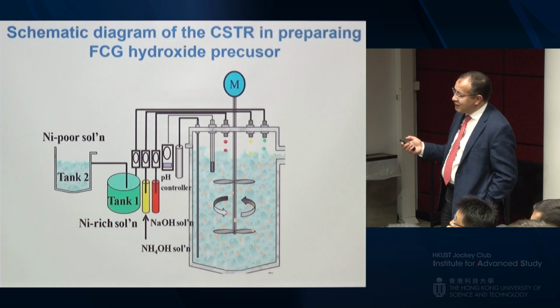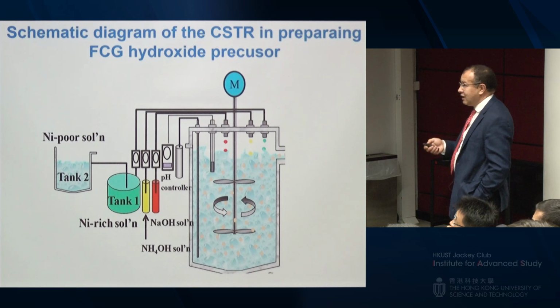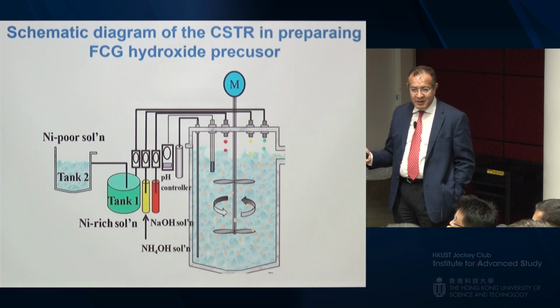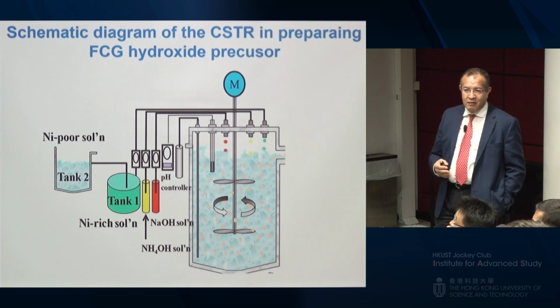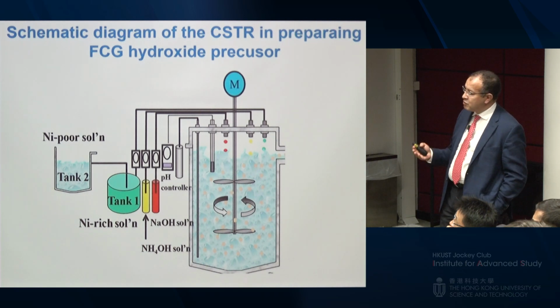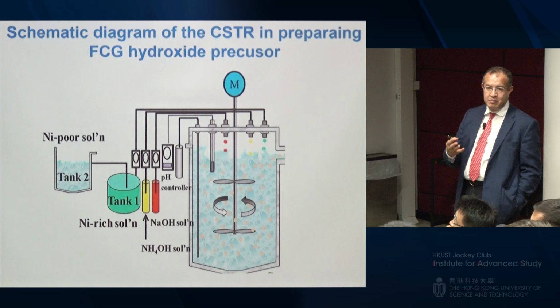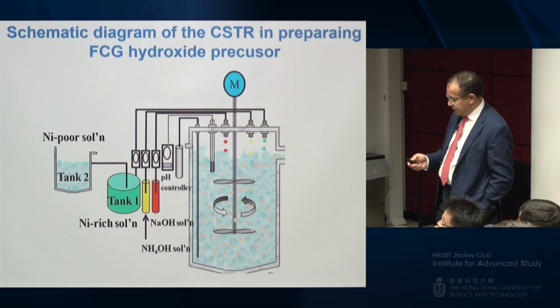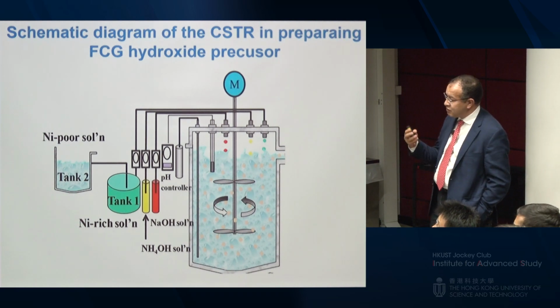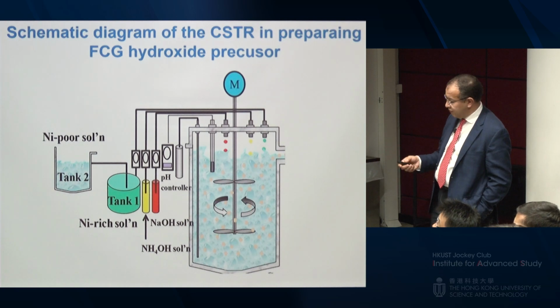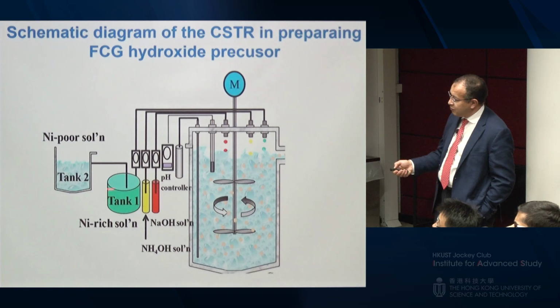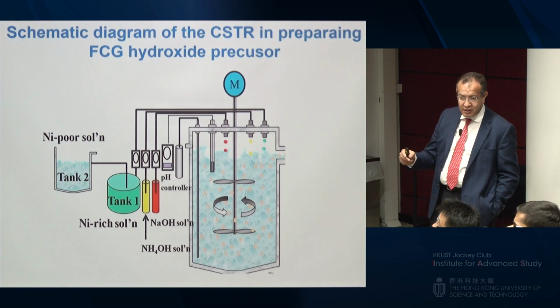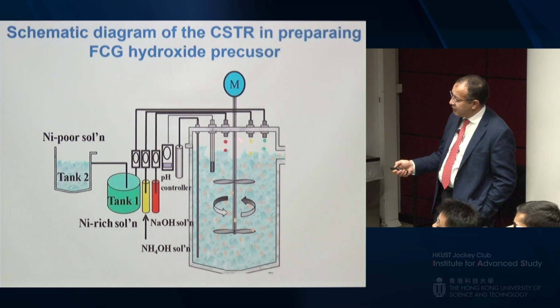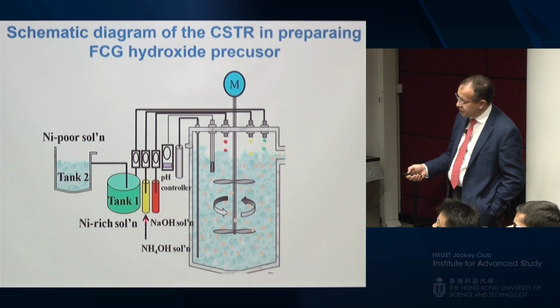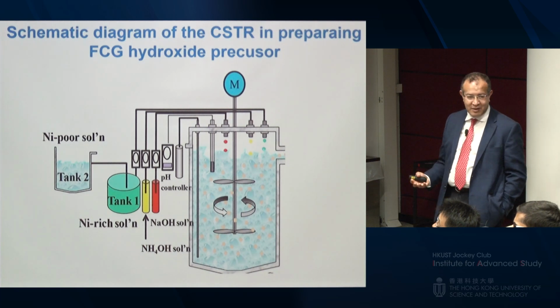So how do you make it? That's the next step. Could you scale it up? And you can just use a simple co-precipitation. This is a very scalable and mass-produced technology for the NMCs and the NCAs that I told you about. In the case of nickel manganese cobalt that is commercially available for automotive now and consumer electronics, they use only this. They put three metals with defined composition in sulfate form and send it to the reactor. You have a chelating agent and a co-precipitating agent, and you make particles.